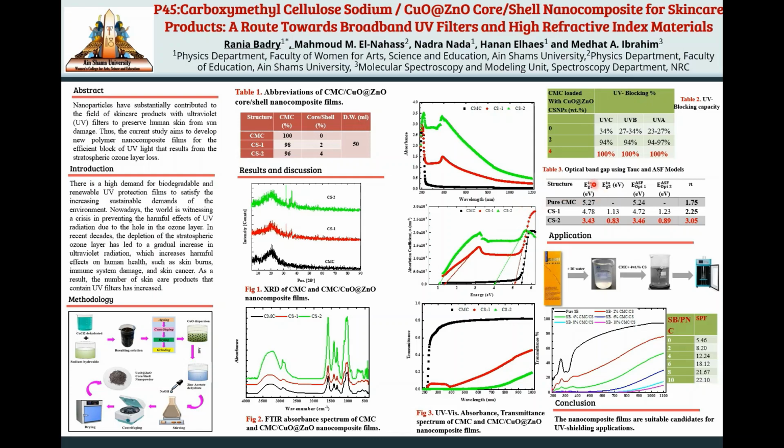Additionally, we calculated the optical band gap using two models, the Tauc equation and the absorption spectra fitting model, and we found that the band gap decreased with increasing core shell nanoparticles concentration, and also the two models are consistent with each other. Additionally, we calculated the refractive index, and it was found that it increased to twice its value with the addition of 4 weight percent of core shell nanoparticles.